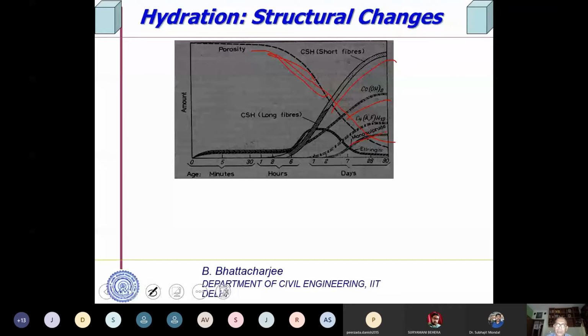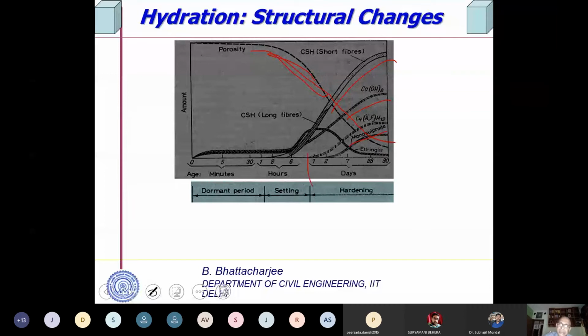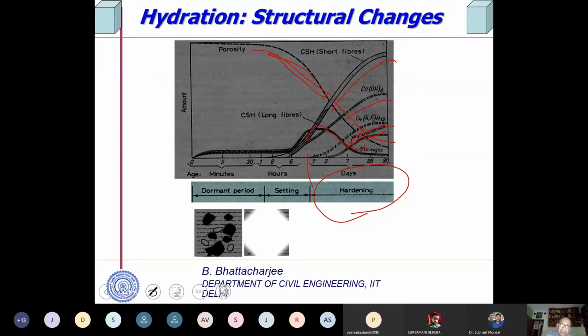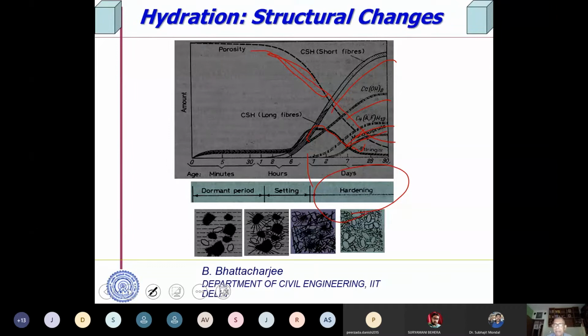I don't think I'll go into the chemistry. So this initial period is called the dormant period, which is your initial setting time. Then the full solidification, around 10 hours, is the final setting time. Then pores get reduced, and this is called hardening, because strength gain will occur during that period. Some products change from one to another, for example ettringite changes to monosulfate. I don't think I'll go into this unless you have some question related to it. And that's how the same model I was showing looks. Initially like this, particle and water, then hydration product, outer product coming as fibers and joining them.